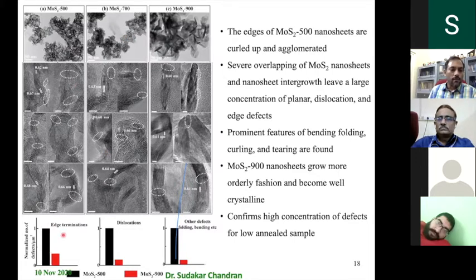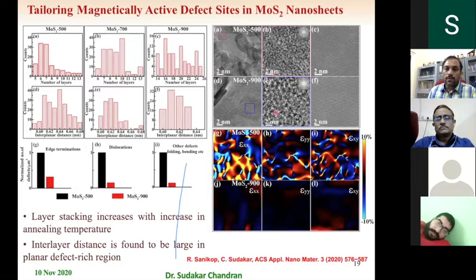We have estimated the concentration of these defects by counting the edge terminations, dislocations, and other folding and bending defects. You can see that the defects are very high when it is a low temperature anneal, whereas the high temperature annealed ones have almost 10 times smaller defect concentration. Okay, so to show what these defects within the plane look like, here is the high resolution image taken from one of the sheets. Of course, these sheets are not monolayer; they are multilayers. For example, you can see the number of layers here. Typically, it is 6 to 7 layers for the 500 degree annealed sample. Of course, it increases as you increase the temperature. So obviously, by the process we used, we cannot keep the thickness the same and then alter the defects. That's one of the disadvantages.